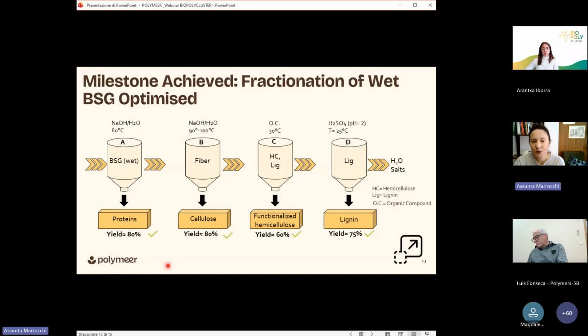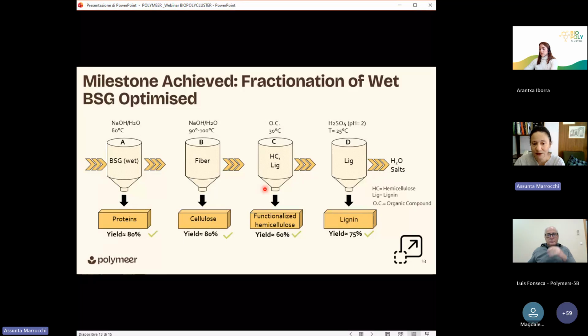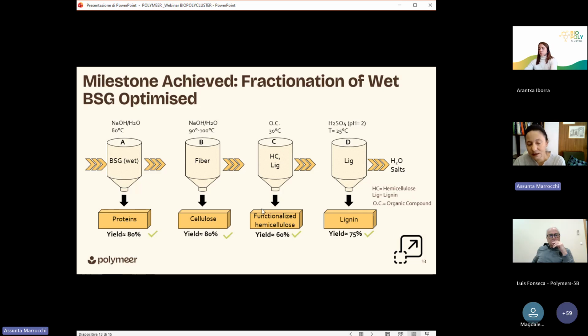What you see here is the sequential process with the extraction yields. It builds on patented knowledge developed at the University of Perugia, which we have now further developed and optimized. Two aspects are particularly important. We process the BSG in its wet state, exactly as it comes from the brewery, avoiding drying, reducing energy use in this way and improving sustainability. And this process also includes reactive extraction steps that enable us to selectively isolate hemicellulose in a functionalized form, which provides added value for subsequent polymer synthesis. So this is the first concrete and resource-efficient result.